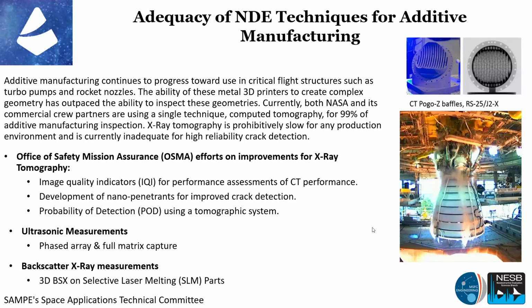So we started working at how do we go down the path of trying to get some of these other things that we normally use in traditional NDE working. So trying to just help generally on X-ray and X-ray tomography. We've got some image quality indicators, and I'm going to show you those in a minute. We did a lot of work in nanopenetrants to help improve crack detection. Certainly, and this is one we're still working through, is establishing probability of detection, which goes a lot into certifying any technique for a fracture critical component. And part of the strength of a CT system is its consistent reconfigurability. You can put a CT system in lots of different configurations, but how do you relate a POD from one configuration to another is an interesting problem. And we're still working through that as well.